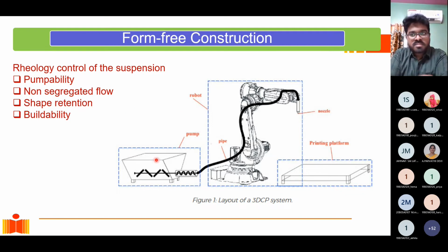We take a mix of, let's say, concrete and put it into this hopper here. It's a pump, which pumps the concrete through this pipe to a robotic arm that deposits concrete in layers in the place that we want. So this concrete has to endure this pressure, go through this pipe, and come out of the nozzle. It has to keep the shape of the nozzle, and as I keep adding layers, the layers already deposited have to take the weight of the additional layers.